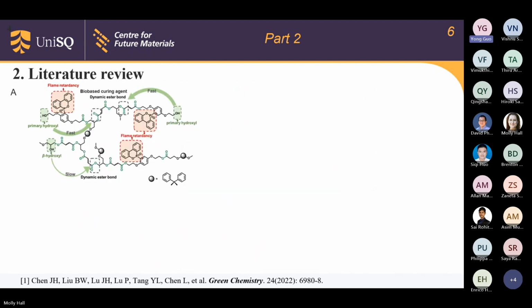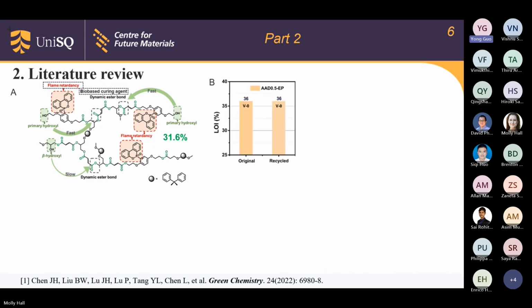Next one, I'd like to introduce the transesterification. First, this system used a bio-based curing agent to cure the commercial epoxy and was modified. This modification introduced primary hydroxyl groups to speed up the transesterification between the dynamic ester bonds to achieve bio-based flame retardancy and recyclability. This system possessed 31.6% bio-based content.